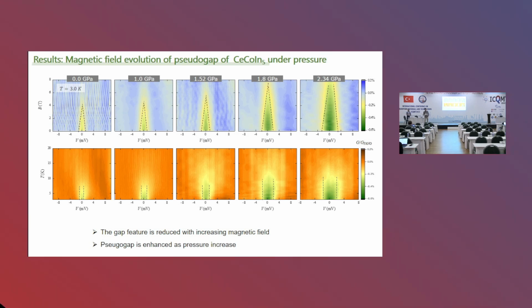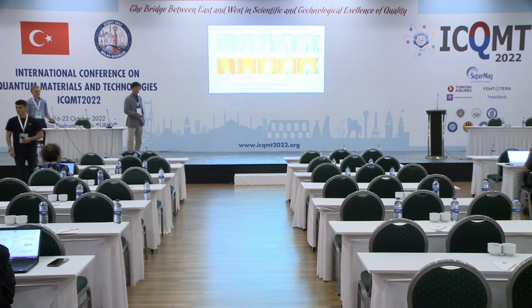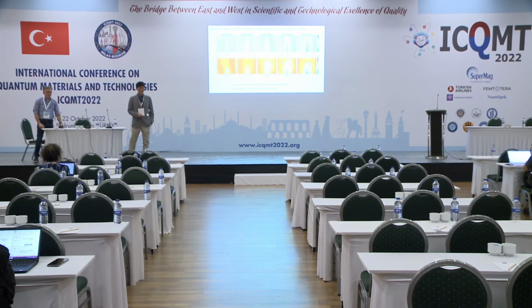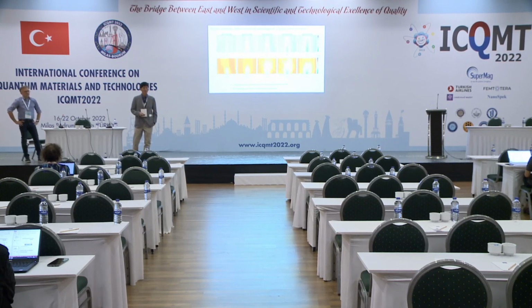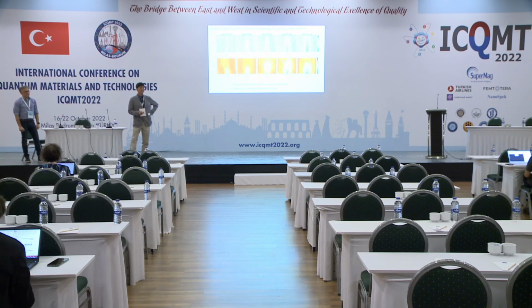Okay, there is another question. Tuson, when we did that back in, I think, 2009 or so, we got the opening of the pseudogap at about 3.3 Kelvin, in line with the measurements at Los Alamos. Now, you reported also data that were a little bit higher. Yeah, you observed 5 Kelvin. Do you have an idea on what this temperature depends on? Is that a surface condition, or does it depend on the measurement you actually do?